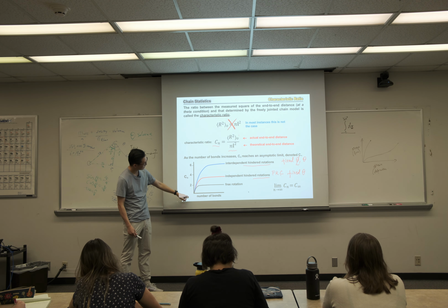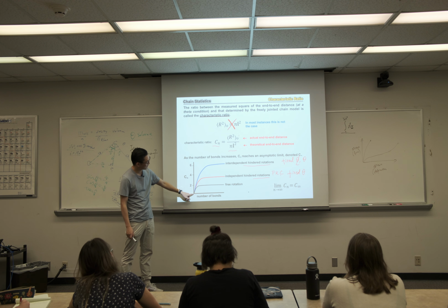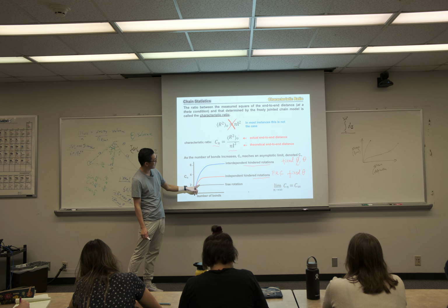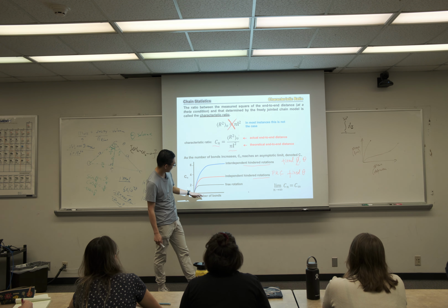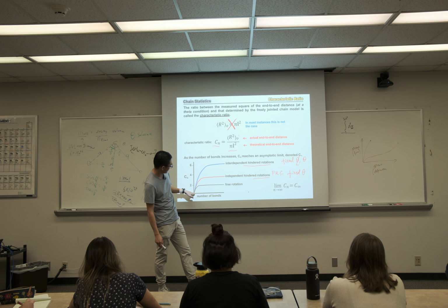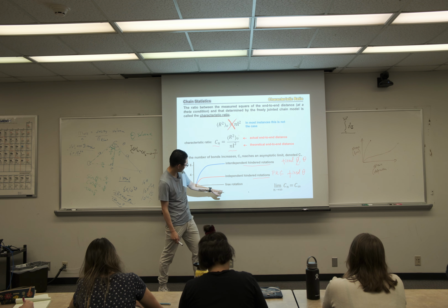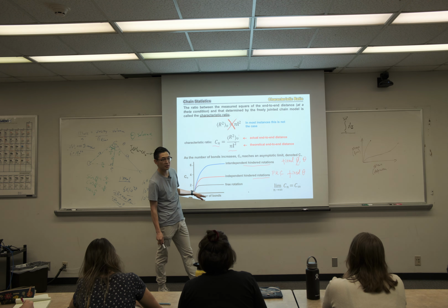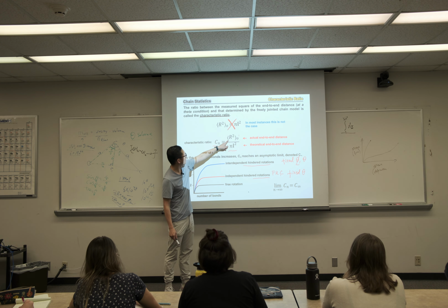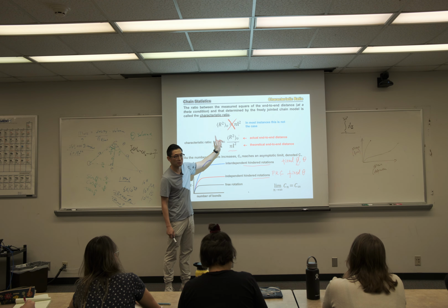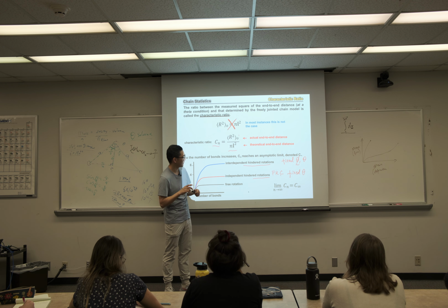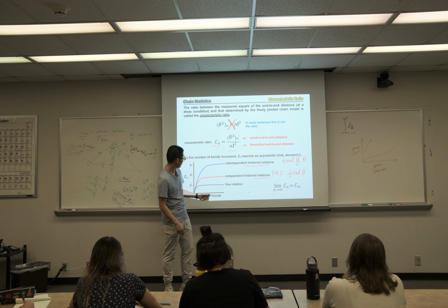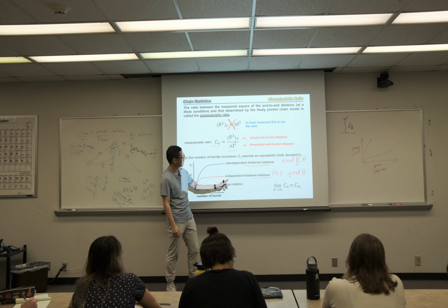Let's look here. For the freely joined chain model, it will always be 1, right? Because for the freely joined chain, your R squared divided by NL squared will be 1. For the freely rotating chain, depending on the bond angle, you can have Cn bigger than 1.